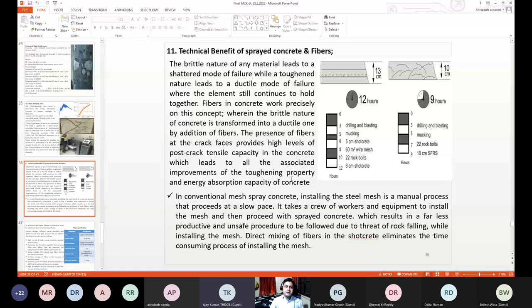You can see on the screen that if the simple bar is being used, your thickness will be higher, and the steel will not be uniform. If you are using the fibers, your thickness will be less, and your fiber will be uniform, well distributed, and will take the distribution of fiber into the structure.